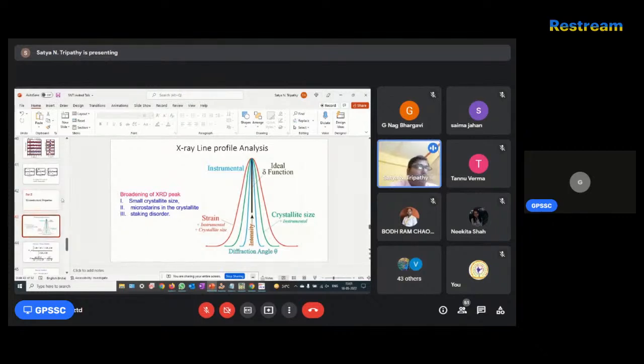An important thing to note is that broadening basically happens at the lower part. FWHM can give you the broadening, but it is an average property. If you want to look for the real broadening, you have to look at the lower end of the peak. This is the peak which you are going to see. The lower end shows you how the peak is actually broadened, so it is very important. Broadening happens due to crystallite size, microstrain, and disorder.